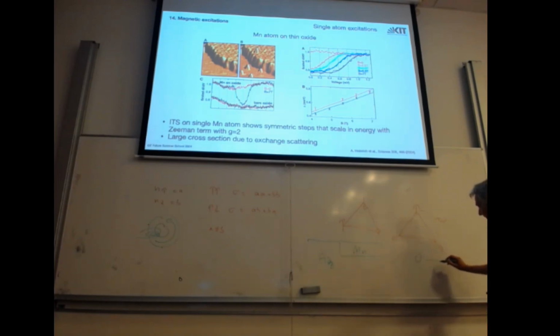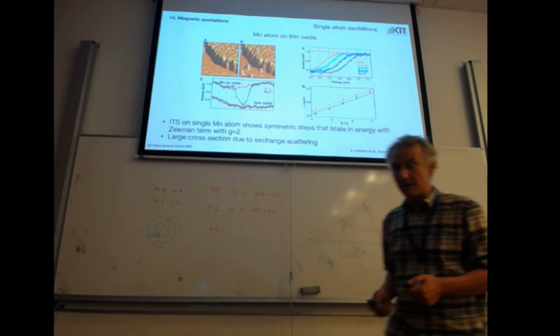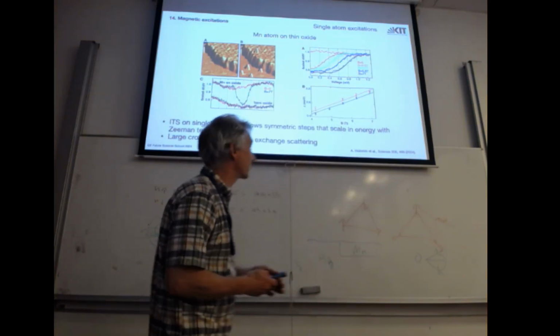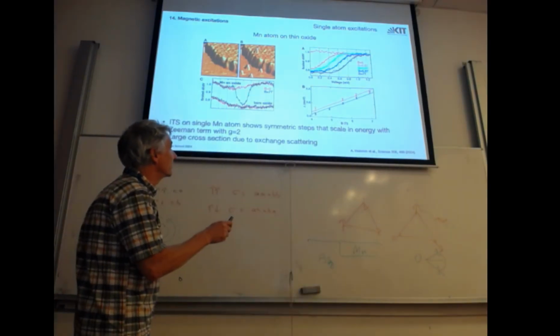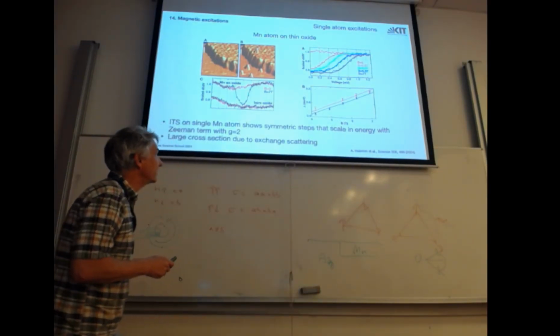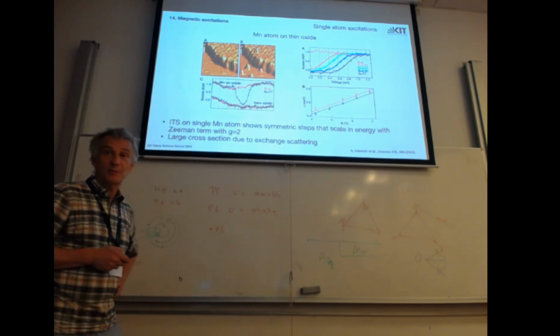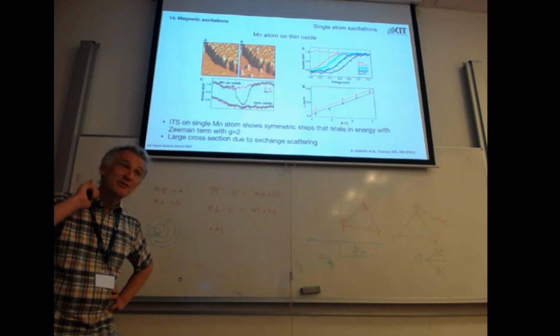I apply a magnetic field, I split my states. And if I do exchange scattering, I can go from here to here. And this is inelastic. This is only possible if my tunneling electron has the necessary energy. This is one step here, this is the upward step in the IV, and this is inelastic tunneling spectroscopy. Now on the spin flip of a single atom.